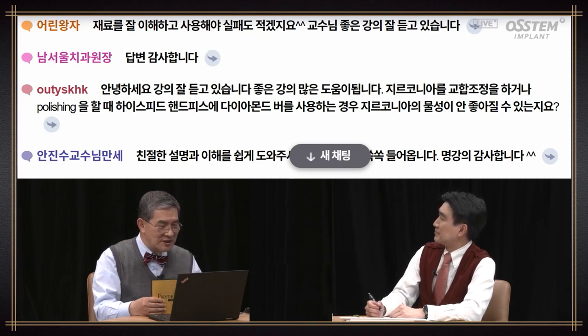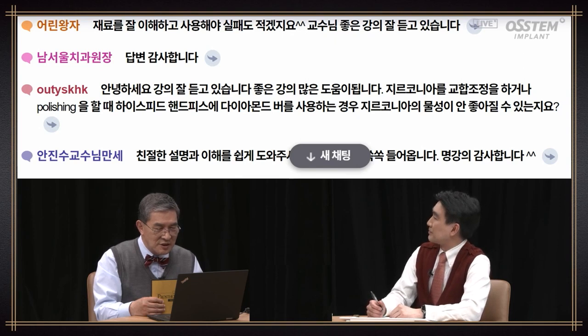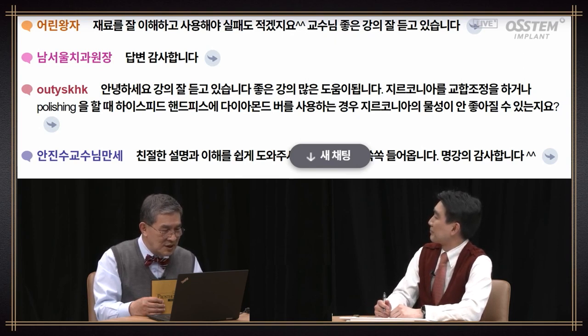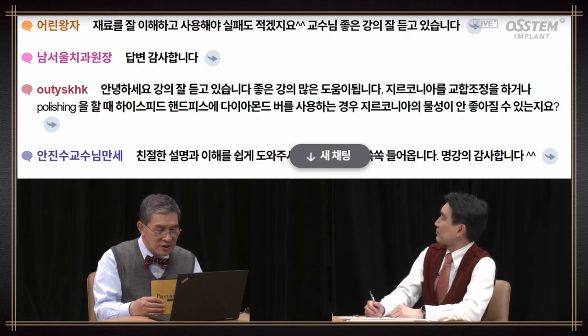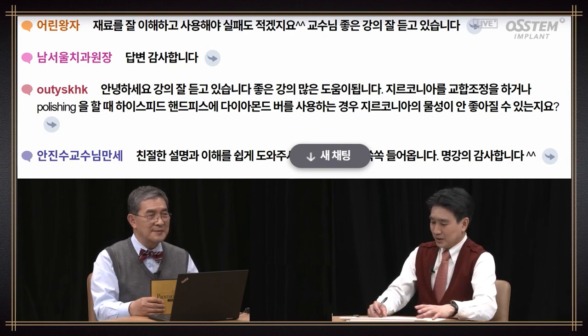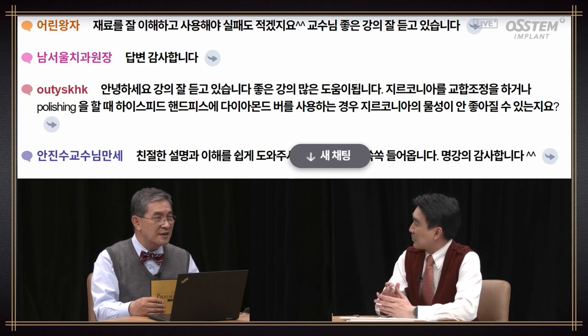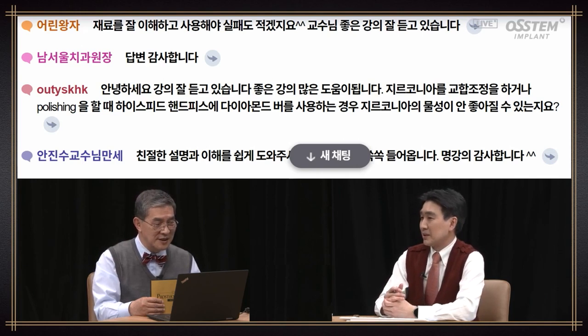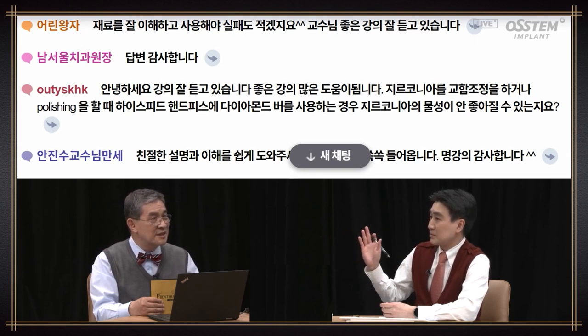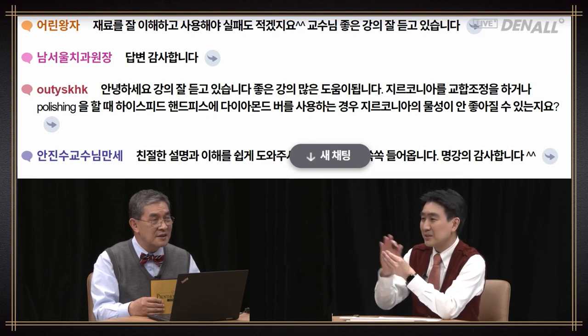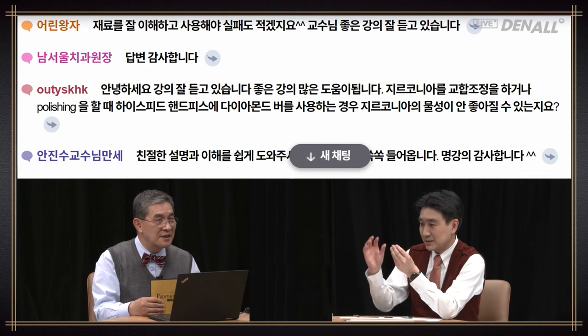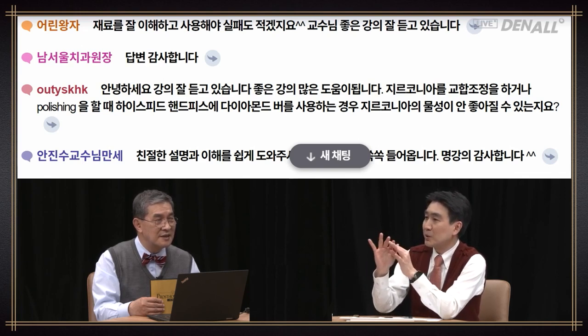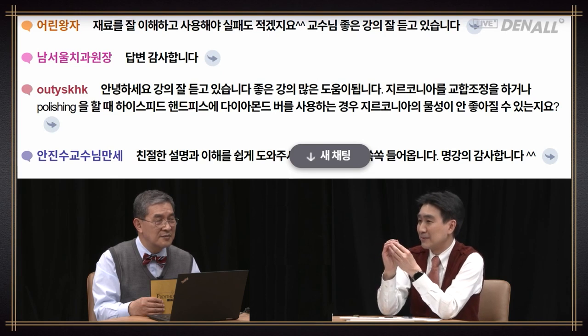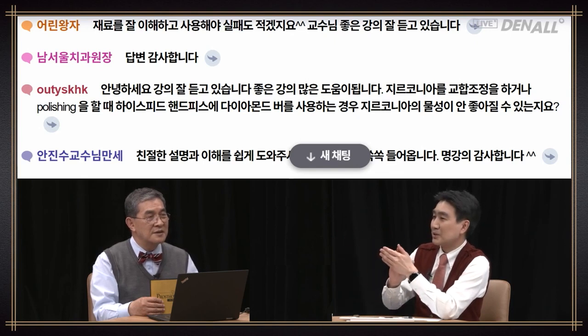I really am enjoying your lecture. It's of great help. When you do occlusal adjustment or polishing, if you use a diamond burr on a high-speed handpiece, can the physical property of zirconia deteriorate? I'm sure you already know about this, but the physical property goes down really badly if you use a high-speed burr. The fact that you touch it with a high-speed burr means you're cracking it. The tetragonal phase is going to change to monoclinic phase, and the surface changes the same as general porcelain. It's not going to have good physical property. Grinding and cutting it off is very negative.